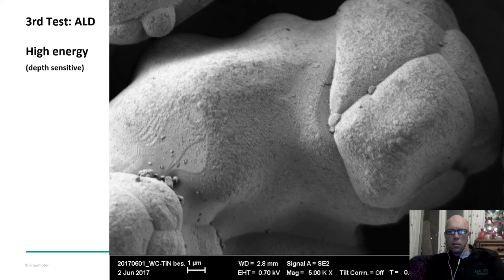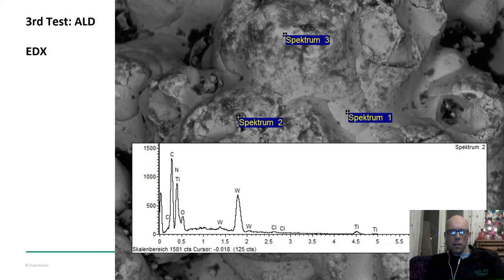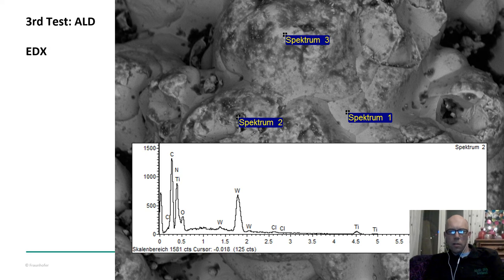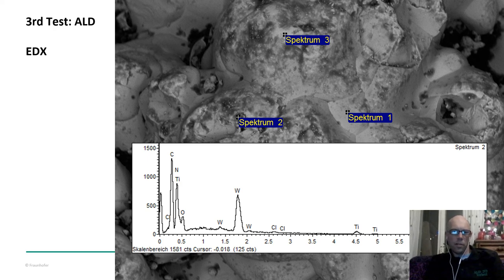We were happy with this result. We also checked EDX — taking different points, using a representative point to confirm tungsten. There's some contamination — a bit of chlorine because of the relatively low temperature — so we definitely get some chlorine left over from titanium tetrachloride. And there are two nice titanium peaks, confirming we have titanium nitride.